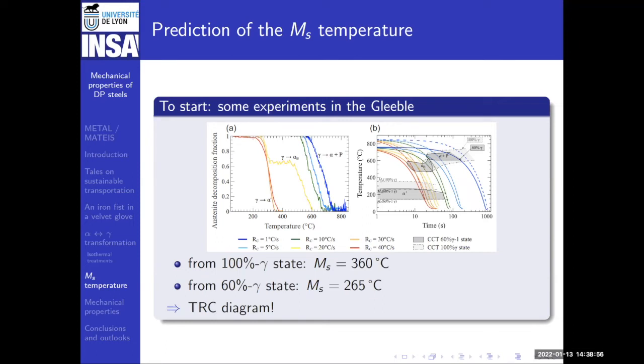And what we could do is do some experiments and measure the dimension of the part in the Gleeble thermomechanical simulator, which is, let's say, a tensile machine able to heat samples. So we have to imagine that we start from high temperature, and depending on the cooling rate, either you form cementite or you form martensite if you quench fast enough. Okay? And thanks to that, we could plot an experimental TRC diagram. And the aim now is to see if we can model the whole diagram. And I'm going to start today with only how to predict the martensitic start transformation temperature.